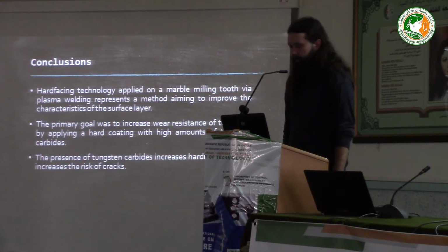So, in conclusion, the application of hard-facing technology on a marble milling tooth by means of plasma welding represents a method whose main goal is to improve the characteristics of the surface layer, mainly its hardness, so that the resistance to wear can be improved. To achieve this, a welded layer with high contents of tungsten carbides was applied, and then the analysis was performed on the presence and distribution of the cracks which always result in case such materials are used.